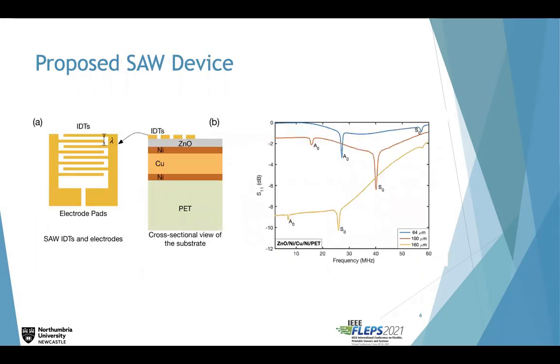Our proposed device has interdigital fingers that are patterned on a zinc oxide substrate as a piezoelectric layer, which is deposited on a tri-metal layer of nickel, copper, nickel, and it is bonded to a PET substrate. We have characterized the devices that have various wavelengths, such as 64, 100, and 160 micrometers.